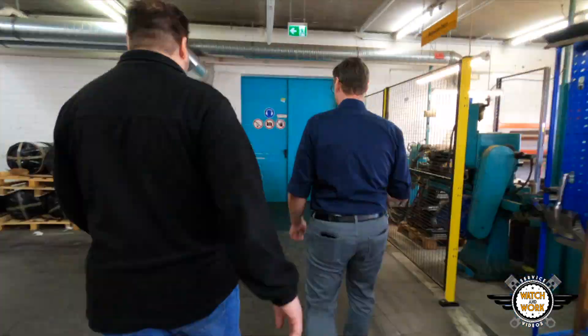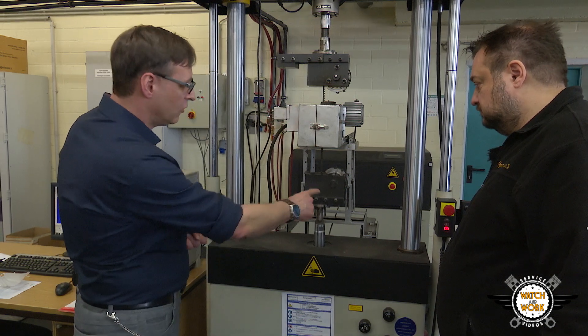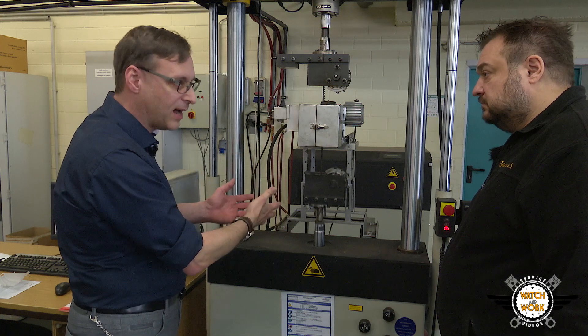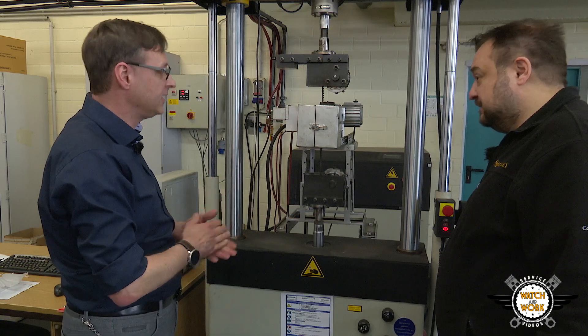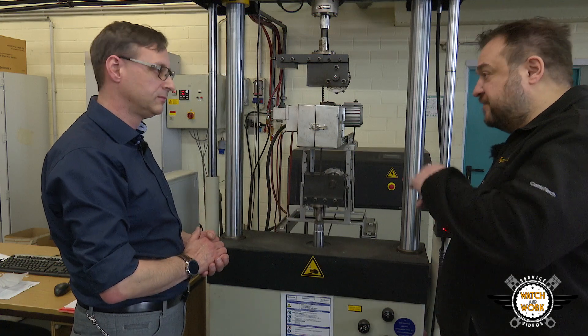We test at higher forces and torques than the belts will actually be subject to. This is our hydropulse shock testing machine. In the middle here we have a heat chamber at a temperature of 150 degrees and a timing belt that has been cut open. Every time there is an impulse from the fuel injection pump, the timing belt is deflected due to the pump's high load. This is reproduced 20 times a second here in this fatigue test. So it's a sort of time-lapse test — exactly, we manage around 1.7 million impulses a day. But the belt will have to endure over 700 million during its lifetime. So we test under overload conditions with increased forces and then work out the belt lifetime at lower forces — meaning the belts have a built-in safety margin again. Exactly.